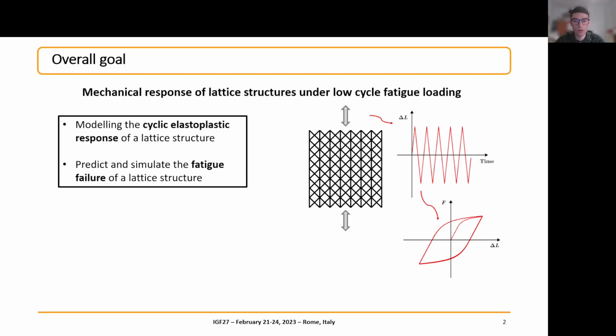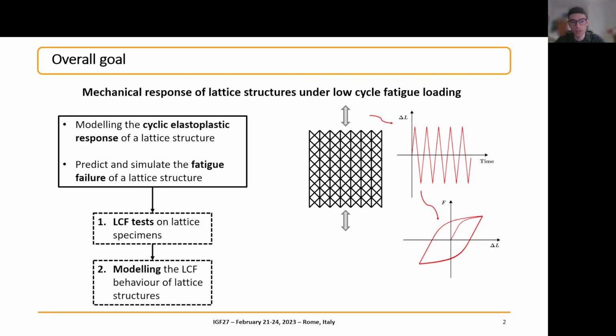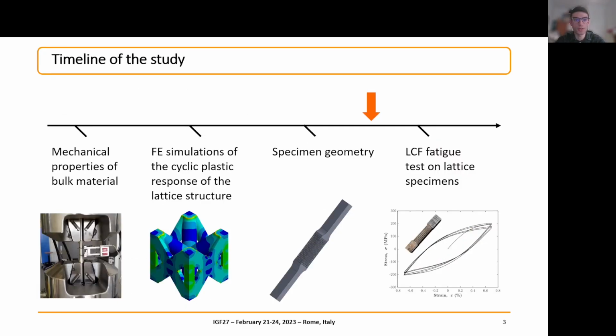So in order to achieve this goal, we must perform some low cycle fatigue tests on lattice specimens and then model the experimental behavior. So here I illustrate the timeline of the study, which is an ongoing project. Until now, we carried out some low cycle fatigue tests on the bulk material in order to model its mechanical behavior. Then we performed some finite element simulations to understand the cyclic response of the lattice structure. And finally, we drew the specimen geometry based on these simulations, the literature, and one experimental test. So the next step is to manufacture the specimens and test them.